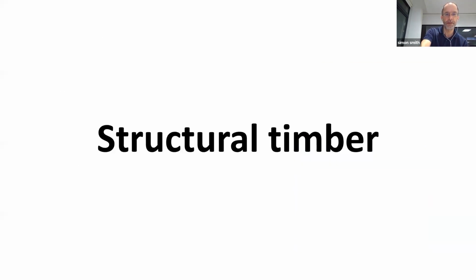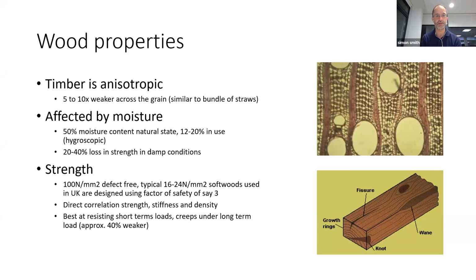In terms of structural timber, don't forget, there's some interesting things about timber. It's an anisotropic material. It tends to be 5 to 10 times weaker across its grain than along its grain. So it's almost like a bundle of straws, which you could squash across the section, but in terms of their length, they're quite strong in compression or tension. Their strength is affected by moisture, and in damp conditions, you can have anything from 20 to 40% loss in strength. Defect-free, it's a very strong material.